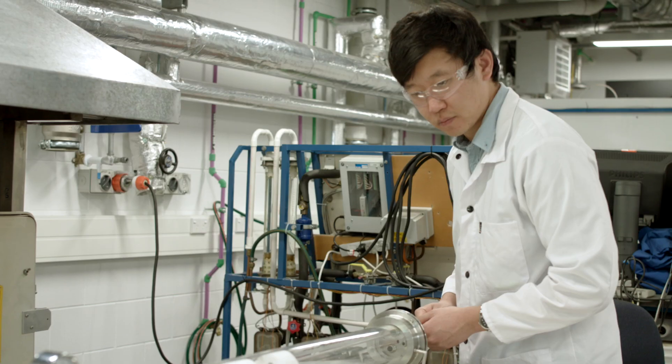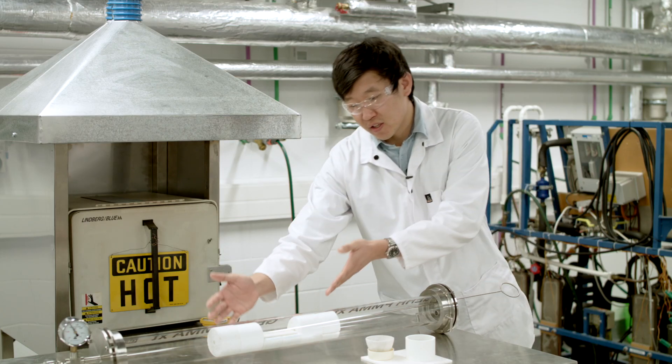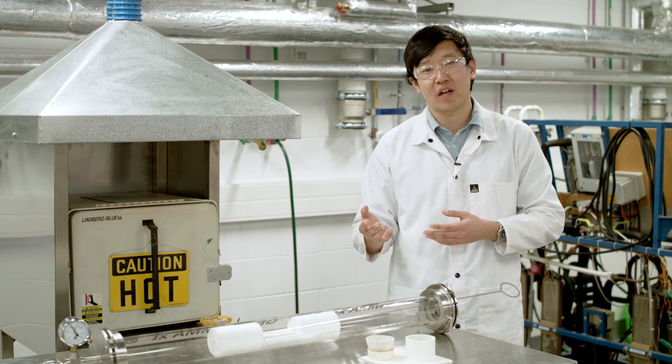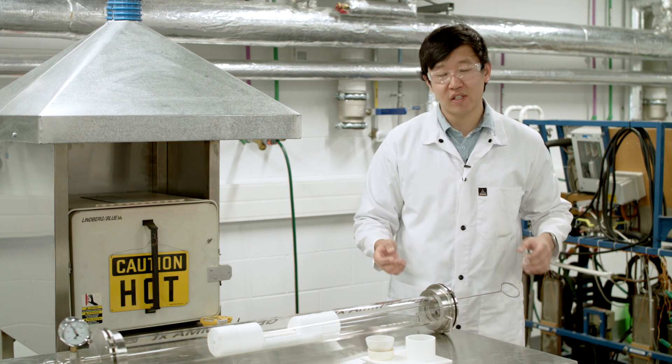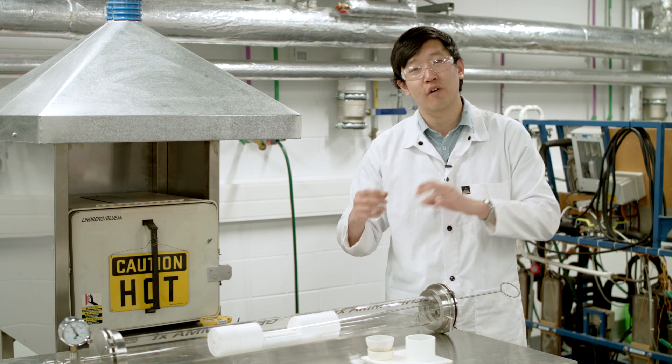So this apparatus here is called a horizontal tube furnace. Currently it's just an assembly scale model, but what I intend to do is stick it into a furnace where this middle section here is in a heated element which heats the sample to 1500 degrees. And then once it's reached that temperature, I will push it up and quench it, which essentially freezes the sample.